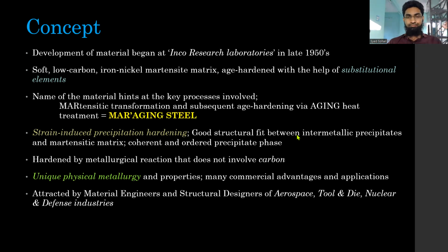Another advantage is that the precipitate lattice is comparable. The lattice size of the precipitate is comparable to the lattice size of the martensite lattice. So there are not many issues in this strengthening, if we can call it that way.